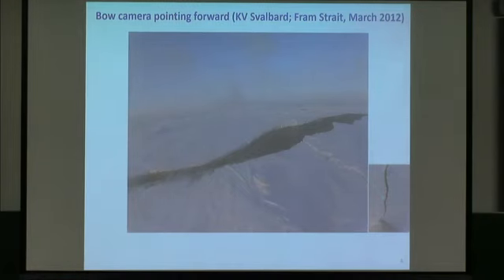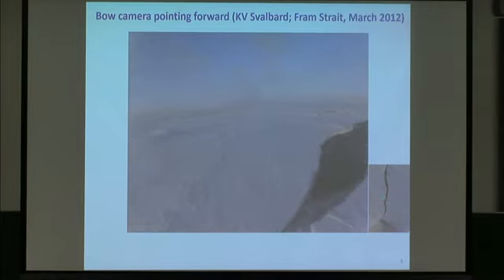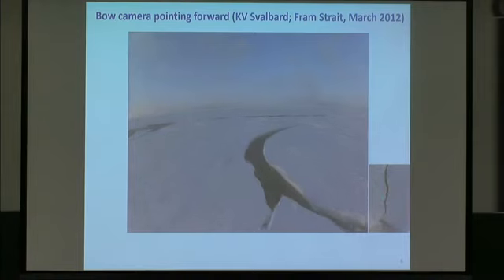On this slide, you see the bow of the icebreaker, and what you will see in the next seconds is a crack running from the bow here when we run into this floe and strike forward. So to let you understand, this is a bow camera pointing forward, similar to what you can see here. This is not the same crack. I run it once more so you can better observe. I haven't exactly estimated the speed of the crack here, but we are more than 10 meters per second. I think we are talking about 15 to 20 meters per second on this crack running.